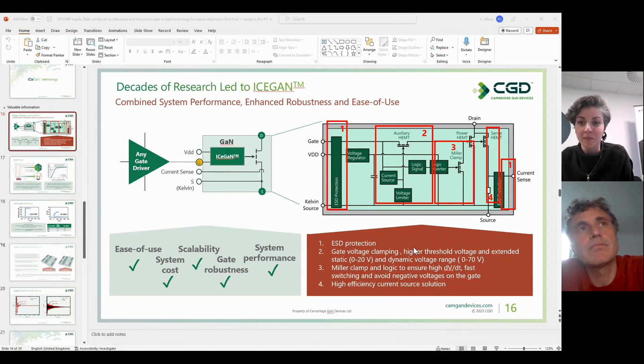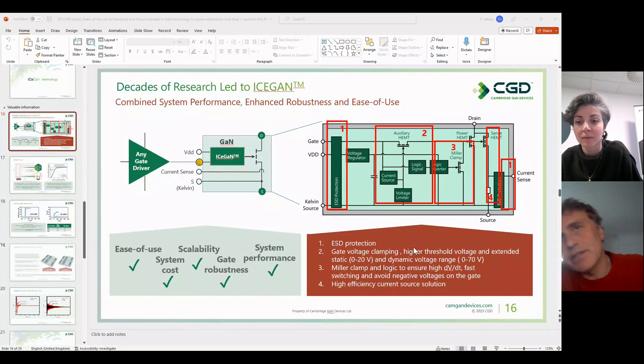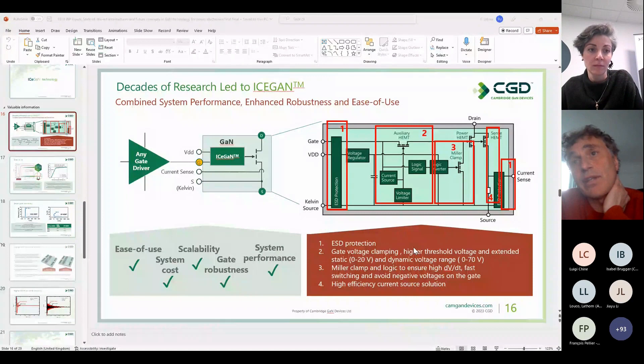From Khan Nisar Ahmed: how do you handle the lower thermal conductivity compared to silicon carbide? Silicon carbide does have better thermal conductivity, but it's a vertical device — when you couple a heat sink to the high voltage terminal, you need an isolation layer with very high thermal resistance. So much of the SiC thermal advantage is lost. For lateral GaN, the substrate is connected directly to the heat sink and is at ground potential, making thermal management actually easier than for a high-voltage vertical device.